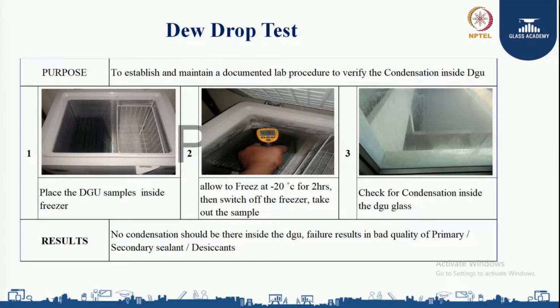Condensation can happen either on the outside surface, the inside surface, or in between the DGU panes. Outside or inside condensation can be wiped out, whereas condensation in between the DGU is not okay. In that case, we need to check the primary sealant continuity, secondary sealant curing and hardness, and whether the butyl and desiccant are able to absorb the moisture.